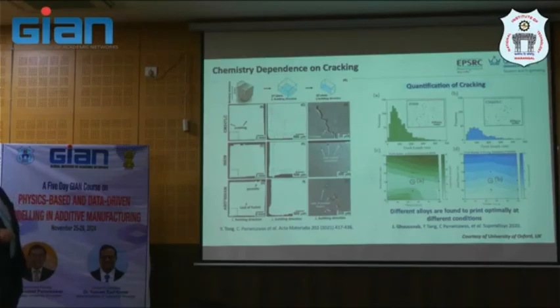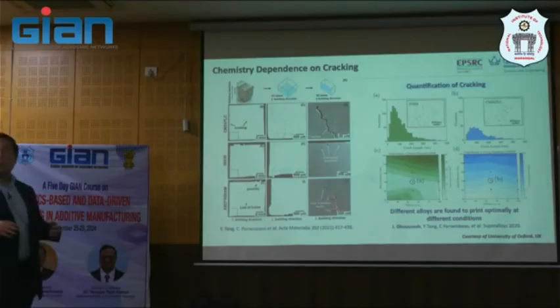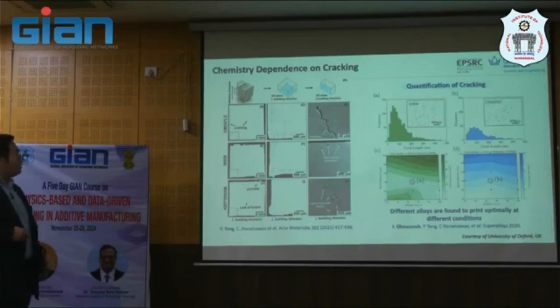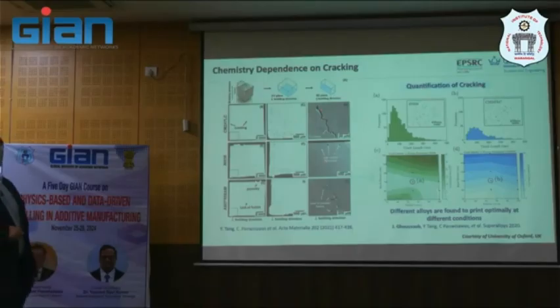So here you will get some lack of fusion porosity, which means it's related more to process parameter optimization rather than other issues. But in other cases, like CM247, it is quite severe. You see, it's a kind of super macro crack that can actually crack your sample, even though this is quite a strong metal.